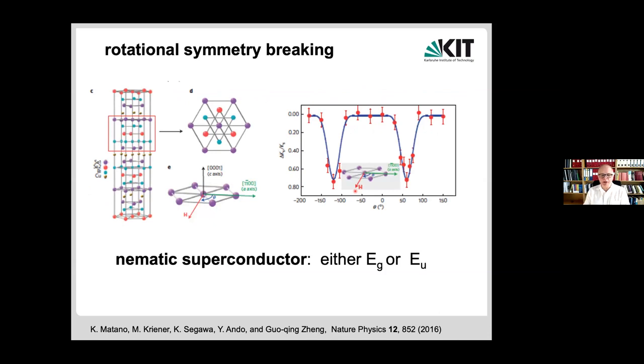These are data here by Guoqing Zheng, where the NMR Knight shift was seen as a function of the field orientation, and we see that the three equivalent axes that you have are not equivalent anymore in the superconducting state, and you basically pick one out of those three, and therefore you have a twofold symmetry breaking in the system. This you would have, and you only would have, if it's one of those two two-dimensional representations in the system. This is a nematic superconductor.